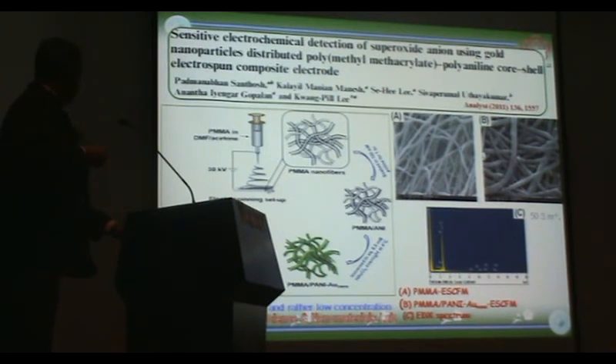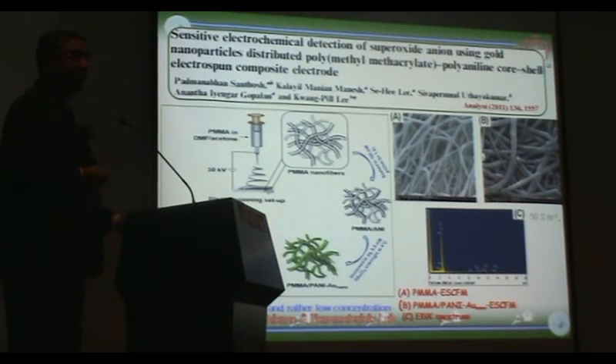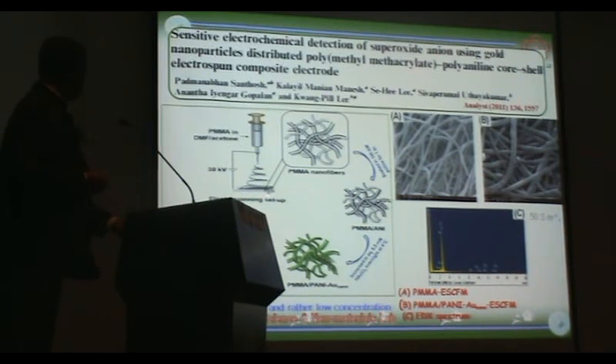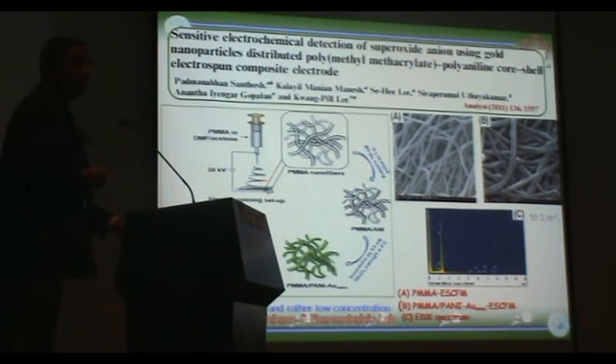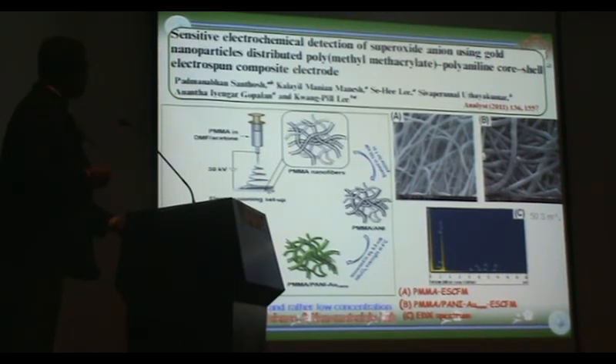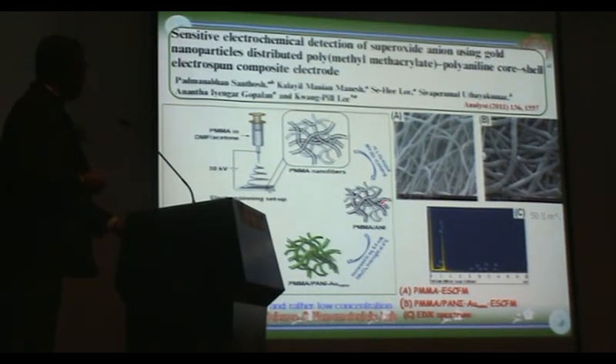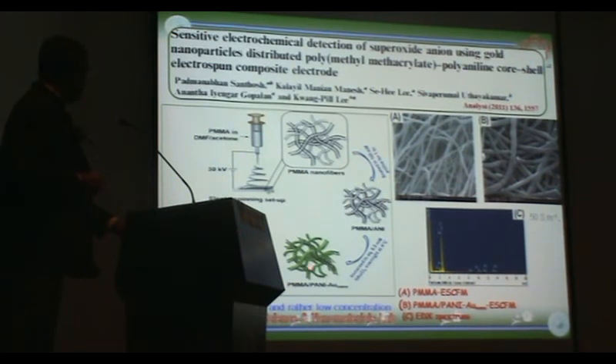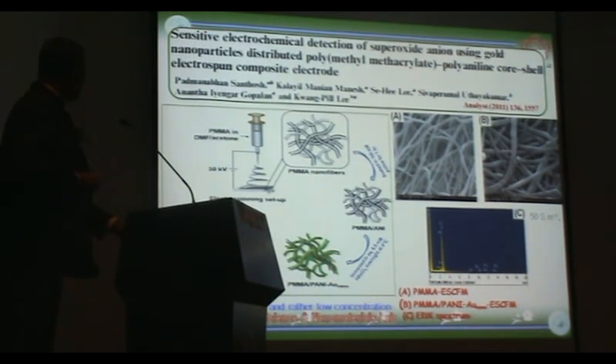The problem is the high reactivity of the superoxide anion, its short life and its very low concentration. All these three combined make the construction of superoxide anion biosensors very difficult. So we try to utilize the electrospinning method for creating the core shell type polyaniline, an electrospun composite nanofibrous structure, and after that we included gold nanoparticle over that, and then we tried to incorporate the SOD in this.